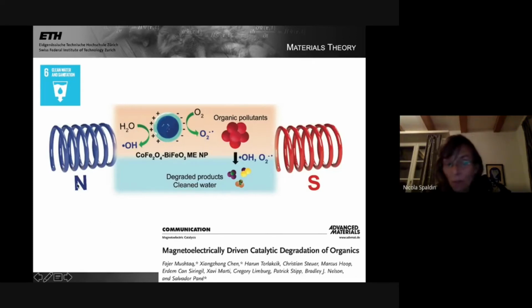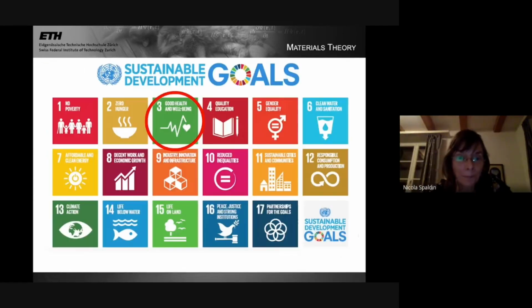And so we talked already about the advantage of using electric fields for saving energy. The advantage of using a magnetic field is that the magnetic field can be applied remotely, right? One doesn't have to contact a system if one's applying a magnetic field. And so in this case, it's the inverse effect that is being exploited, the fact that the magnetic field is changing the electric dipoles in the bismuth ferrite.